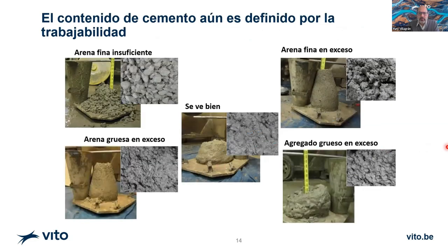These mixes are also more sustainable and increase the efficiency in the use of cement. Another consideration in the use of concrete is how the cement content is defined. We use concepts such as strength and durability, but in reality, oftentimes the cement definition is done by the workability. That is, we incorporate cement to fill the gaps of the aggregate. So having a better granulate structure allows us to reduce the fine cement material and even couple cement with another fine filler to fill the spaces better without having emission costs associated.